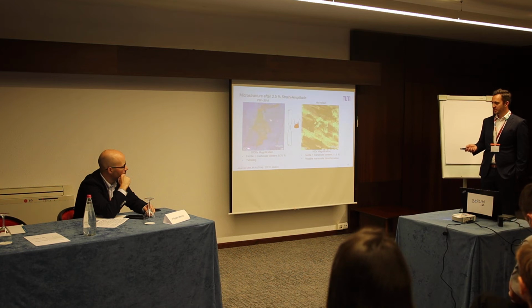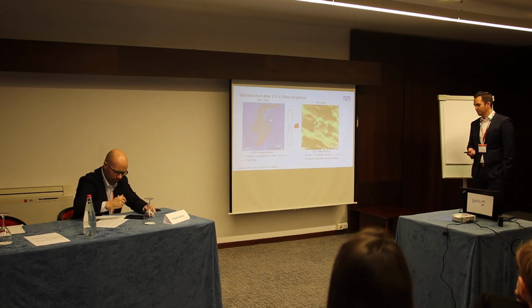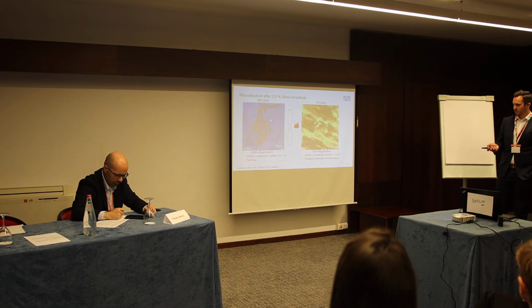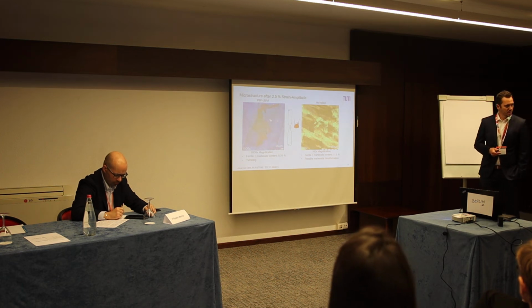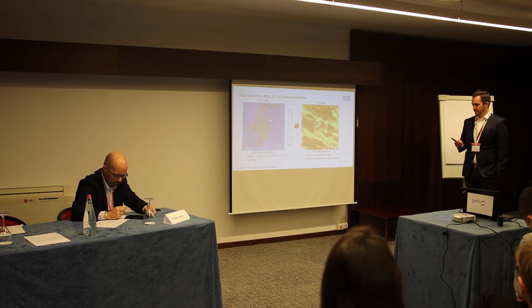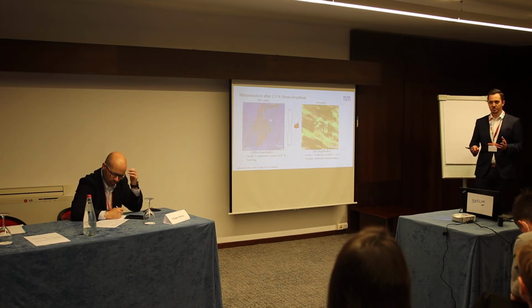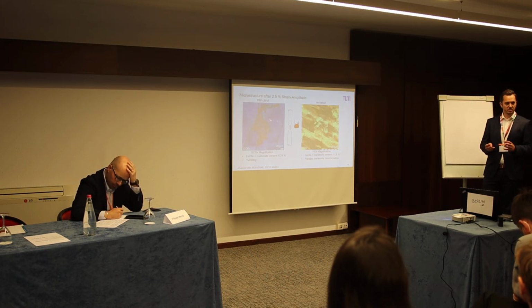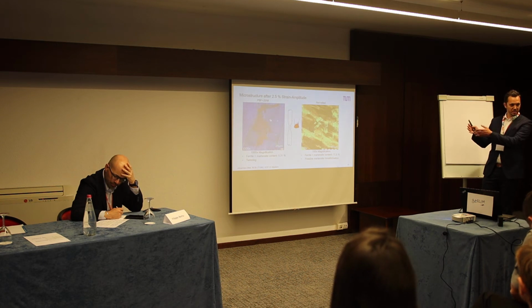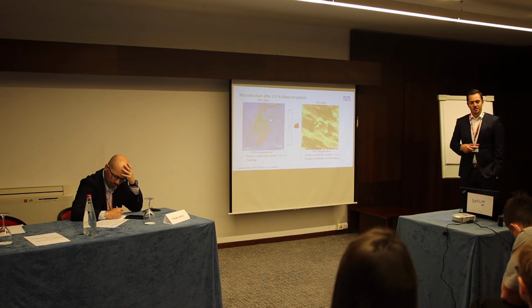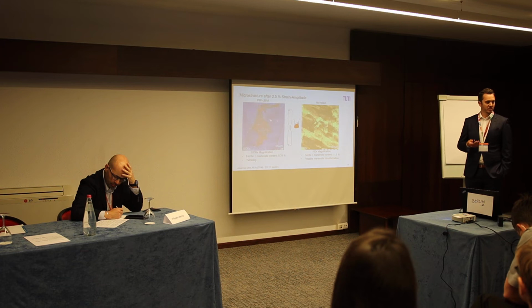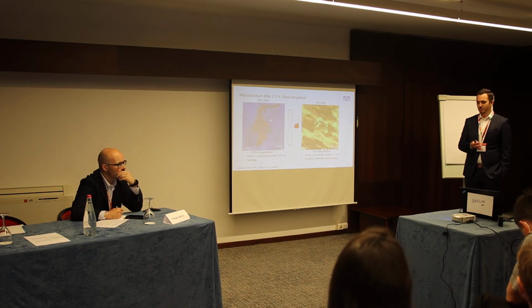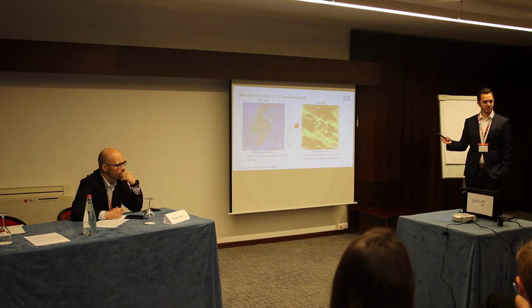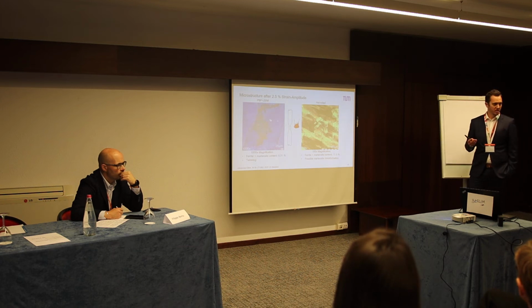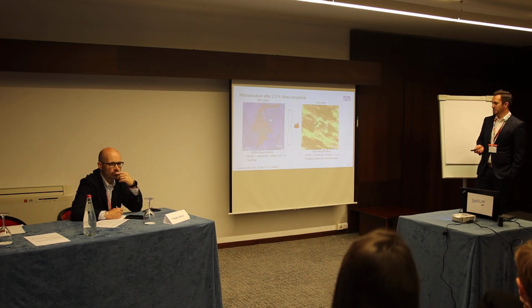Here we measured a ferrite or martensite content of 0.31%, and we also saw some twinning. We used the Feritscope to measure the ferrite or martensite content, and the problem there is that it cannot distinguish between ferrite and martensite, so that's why I'm saying it could be both. But because we have only, or mainly, austenite, we have an austenite to martensite phase transformation during the induced plasticity in the end.